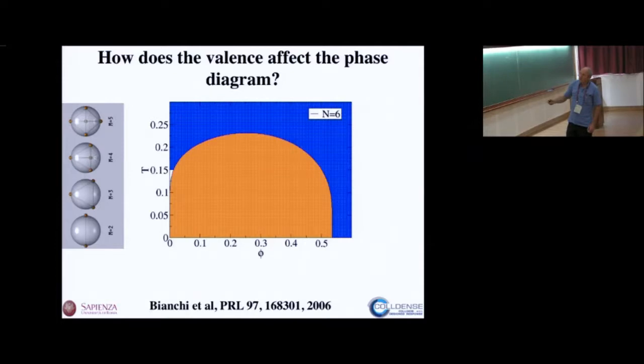And you can continuously tune the number of patches that you put on your sphere. You can go from 5 to 4 to 3, and at the end to 2. We discussed the case of 2, the equilibrium polymerization case, in the previous lectures. So let's see what happens if we do the calculation of the gas-liquid phase coexistence in the case of a particle, let's say, with 6 patches.